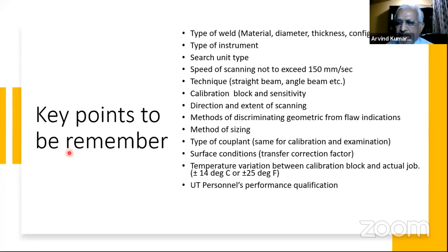Direction and extent of scanning. Sometimes there are limitations with respect to extent of scanning, which should be reported in the report that you get, so that you know where things were not able to be detected and what actions you have to take. You should be aware of that. Methods of discriminating geometric from flaw indications. Now in ultrasonics, many times you get geometric indications. Unlike PT, where it is very easy to make out what indication is relevant and non-relevant, in UT, unless the operator has skill, he will not be able to find out whether it is a real defect indication or an indication coming from the surface because of spatter or a small undercut. One should know how to differentiate a real indication from a geometric indication. You have to actually plot the weld at 1:1 scale and plot the beam, how much it has traveled from where you got the indication, to decide whether it could be real or geometric.